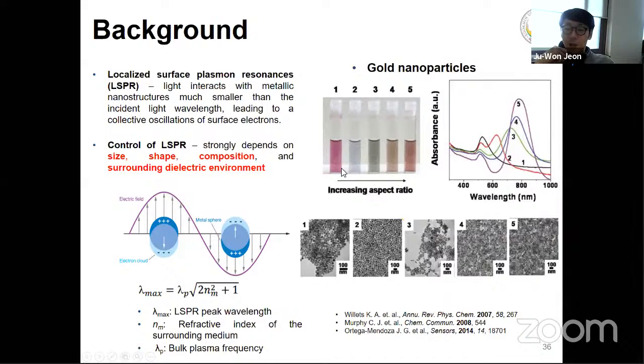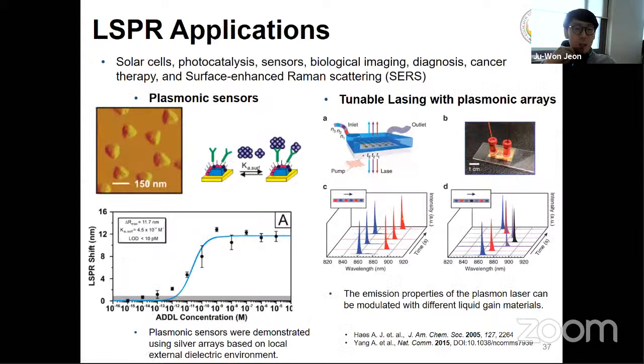But if you synthesize a gold nanorod, the color changes depending on the aspect ratio. So there is another longitudinal LSPR property emerging, and it shows a very sharp and very strong longitudinal LSPR peak. This LSPR can be utilized in various applications, including solar cells, photocatalysis, sensors, and biological imaging. For example, plasmonic sensors were realized to detect Alzheimer's disease.